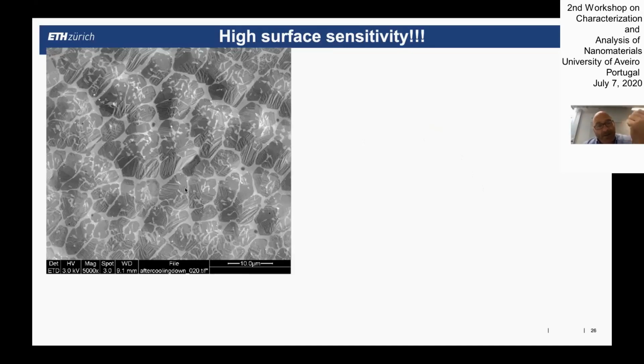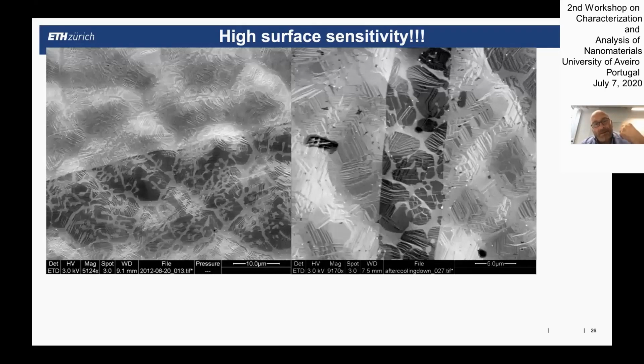And the funny thing is, we took out this sample, and a few days later, we put it back into the microscope. And then we realized that on some grains, the graphene is dark still, and on other grains, the contrast has completely changed. This is another example. The graphene is everywhere, but on this twin here, the graphene has dark contrast, and on the other side not.